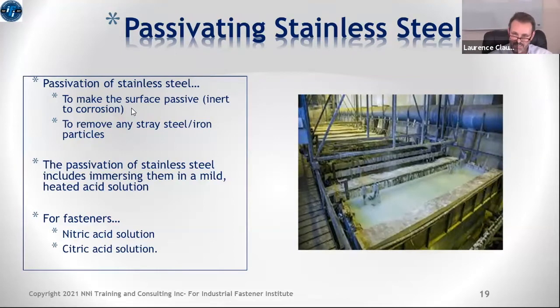Well, what happens is that stainless steel has an affinity for ferrite, free ferrite. And so if parts during the manufacturing process or during the processing of the parts are exposed to steel somewhere along the way, so let's say in the manufacturing process they're collected in steel tubs and the part strikes the side of the tub, it's possible that some small particles of ferrite or iron basically slough off and attach themselves to the surface of the stainless steel. And once the part then gets out in its service environment, or an environment where it's a little bit moist, that little piece of iron rusts and you get these little rust spots forming on the surface. Passivation takes care of that. Passivation cleans all that contamination off, and then by making it passive, more inert, it protects it from that happening again in the future.